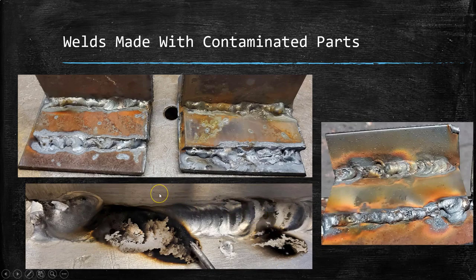And another thing that can lead to contamination is simply not cleaning your metal. So in all three cases of this carbon steel here, we see that there's rust on the metal and you don't see any grind or polishing marks. So that's another way that our tungsten can become contaminated. If you're trying to weld over oil, paint, grease, rust, mill scale, anything like that, when you're using GTAW, you need to take that extra time and effort to not only make sure that the parts you're welding with are clean, but you need to make sure that the metal you're welding on is clean as well.